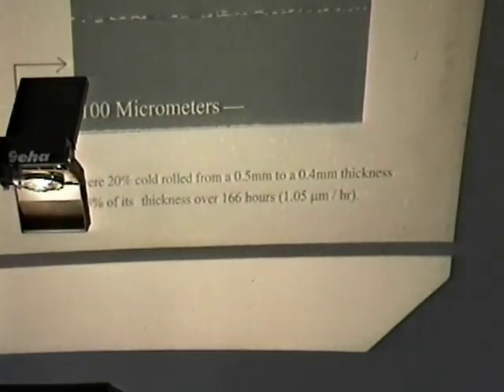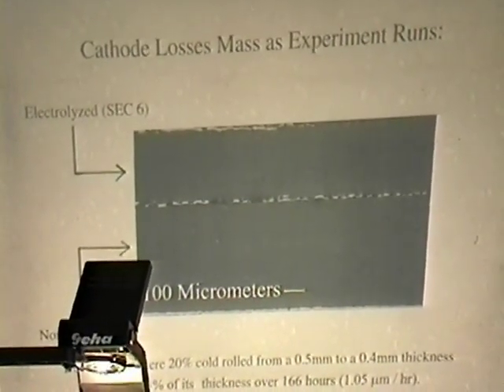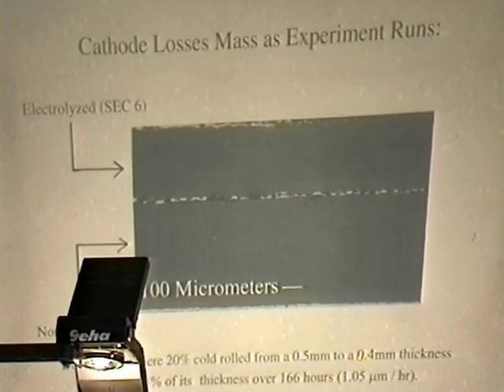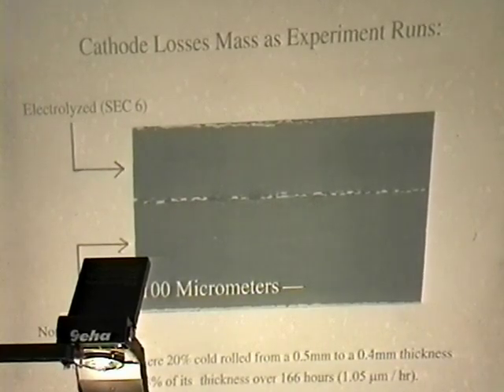Now, one may argue that this is deposition from somewhere inside the cell during the experiment. And what I'm going to show here, these two pieces of metal, this is a little dark, but these two pieces of metal are cross-sections of cathodes that were the exact same thickness. They were both 20% cold rolled from 0.5 millimeters to 0.4 millimeters thickness. And what you see is that over the lifetime of the experiment, the electrolyzed cathode eroded, it lost thickness. In fact, this one lost 43% of its thickness. This one has not been electrolyzed at all. The rate of this erosion is about 3 angstroms per second, as it turns out. Now, this erosion is pretty typical for the cathodes that we have.